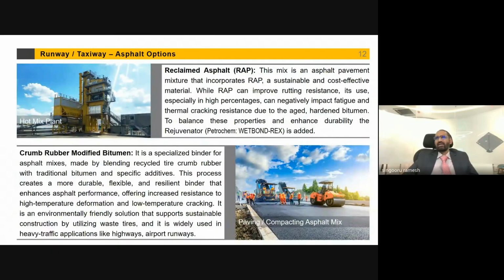The RAP we discussed earlier. This mix is an asphalt pavement mixture that incorporates RAP, a sustainable, cost-effective material, where RAP can improve rutting resistance. Its use, especially in higher percentages, can negatively impact fatigue and thermal cracking resistance due to the aged, hardened bitumen. To balance these properties and enhance durability, the rejuvenator, Wetbond REX, is added, because the RAP material will be aged and will have a negative impact on fatigue resistance. So for that, this Wetbond REX material will be added as a regenerator.